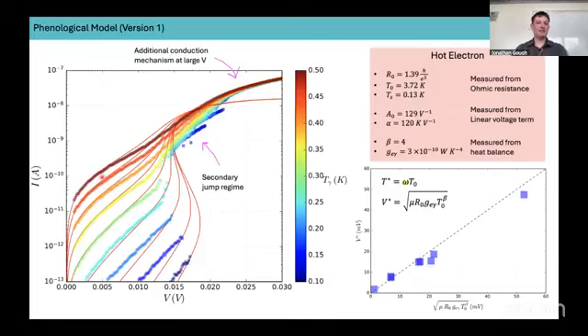And we find that this model works extremely well in describing our data, which is obviously very unusual for a strongly localized system. There are two areas where we still need to think of additional effects. The first is this secondary jump regime, where the model predicts that you should be temperature independent here. However, we still see this temperature dependence and also these secondary jumps. We also have an additional conduction mechanism coming in at very large voltages, so the prediction is less than what we experimentally measure.